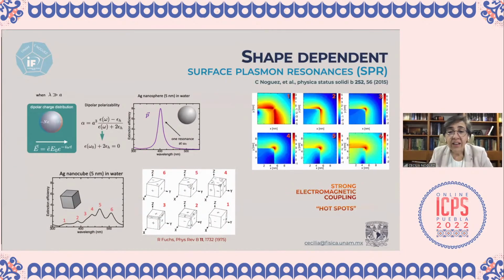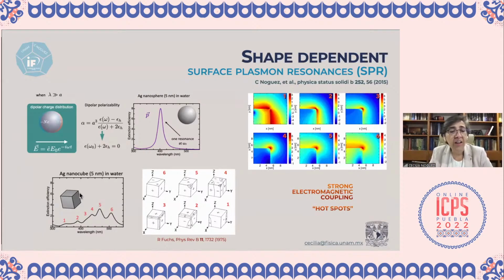Okay. As I told you, when we have a silver cube, a nanoparticle made of silver, and we have a nanocube of 5 nanometers, in this case, immersed in water, we can find 6 different modes. In this case, we have identified 1, 2, 3, 4, 5, 6, and the charges are arranged completely differently in all these modes. Okay, and now, for example, you can see that the Coulomb forces are quite different as compared with the spherical one. Okay, and for each of these arrangements of the charges in the nanoparticles, you will have a resonance where the external force and the Coulomb force, given that charge arrangement, are equal.